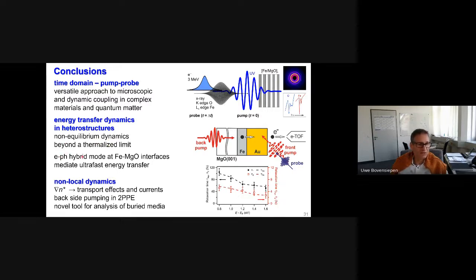I could show you this electron-phonon hybrid mode at the iron-MgO interface that really mediates ultrafast energy transfer via phonons. And then I looked into non-local electron dynamics, where we have transport effects and currents in this new backside pumping configuration in two-photon photoemission, which is a novel tool for analysis in buried media.